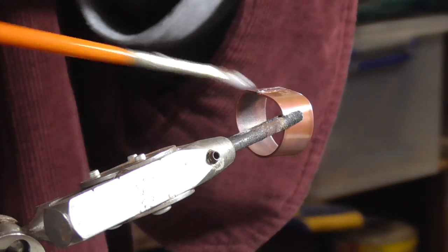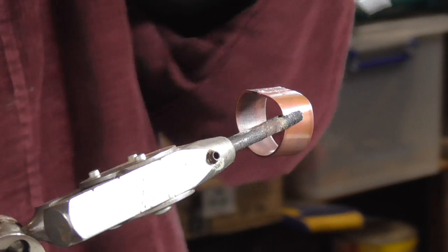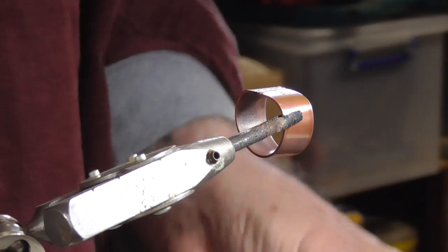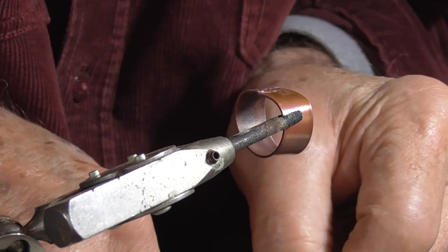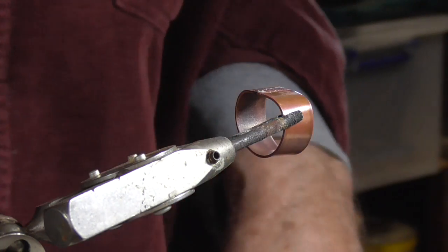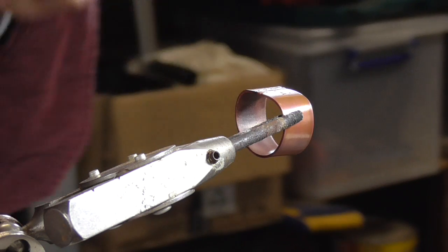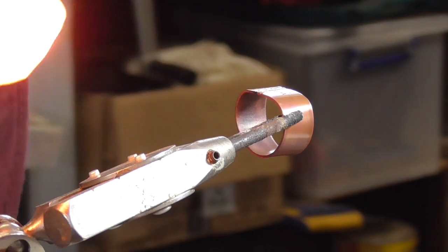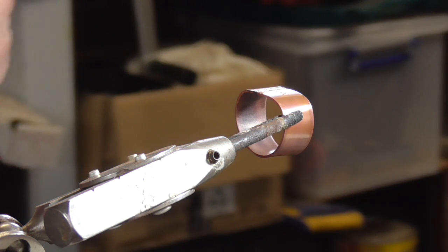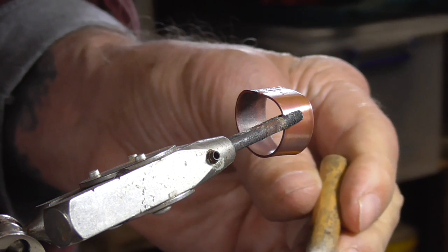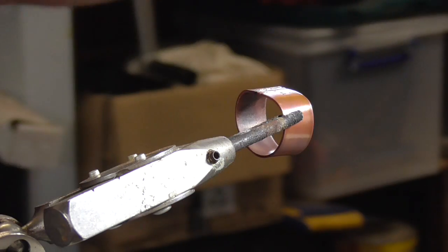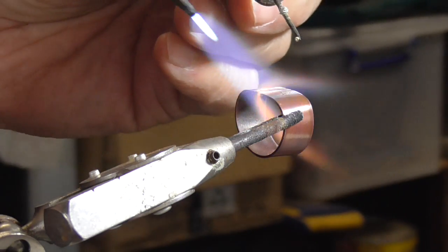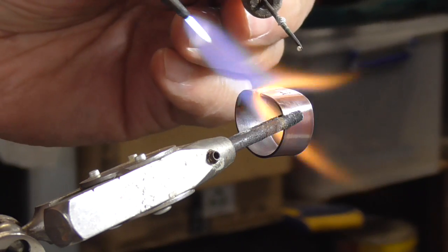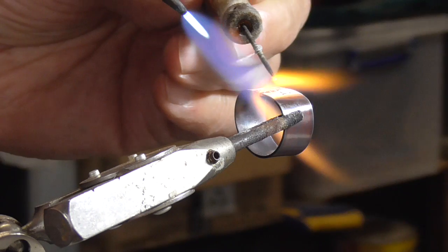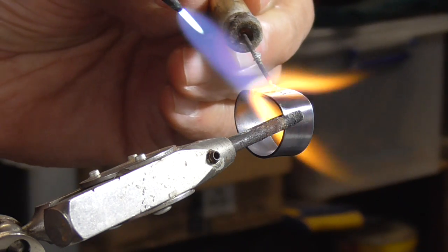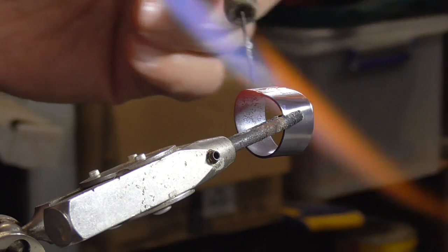So a little bit of flux top and bottom, and 2 more pieces of hard solder. These are only about 1.5 millimeters long. You could place them on the ring with your flux brush, but I find it a little bit quicker to actually use the solder pick. So I'm just heating the joint. Make sure that your flame is straight on so both sides of the joint are the same temperature. Otherwise your solder will jump to the hottest side. So there we go.